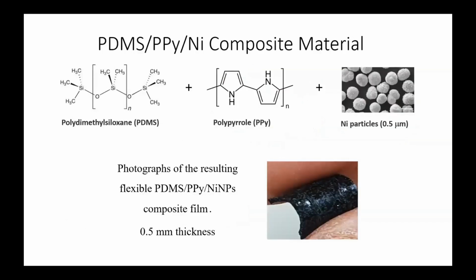It is very, very simple to produce. We take a very common polymer that every lab uses, polydimethylsiloxane, PDMS. We blend this polymer with another polymer, which is a conductive polymer, polypyrrole, and we implant nickel particles in it and blend, and we have this film. This film can respond to multiple stimuli. The thickness is around half a millimeter, and it's very flexible.